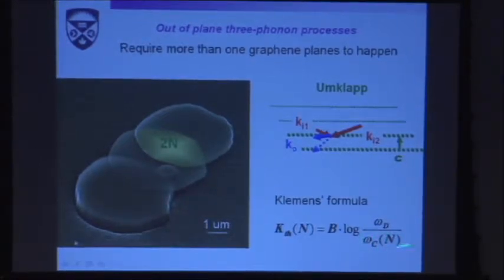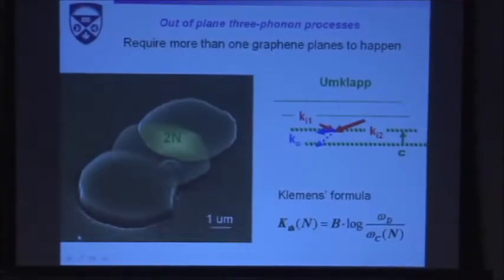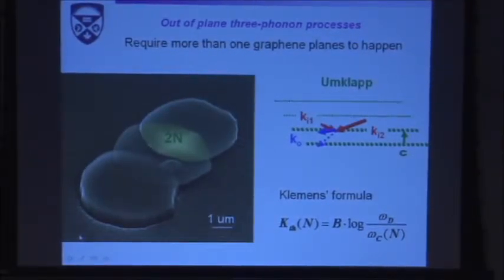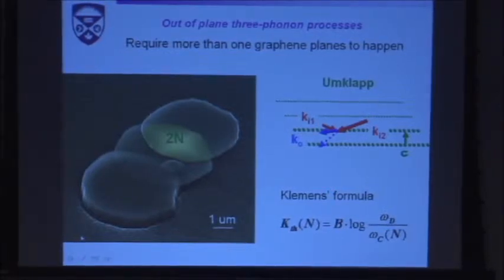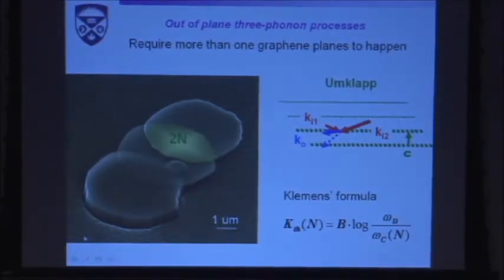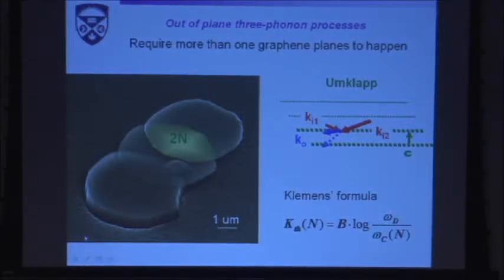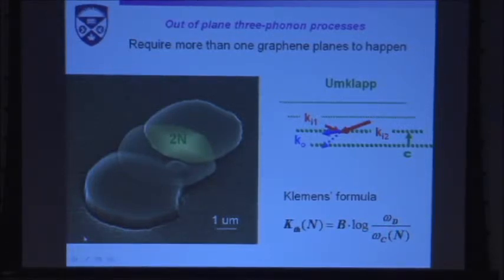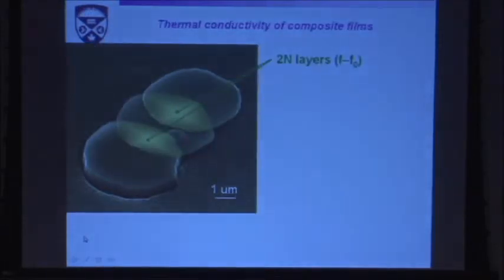Basically, this goes down when you have more layers, because if you have more layers, you may have more incoherent vibrations between layers. So these umklapp processes are encouraged. This number gets much bigger than 1, and the thermal conductivity goes down. Not so much, however, it goes down in a logarithmic way, so it goes down in a pretty difficult way.